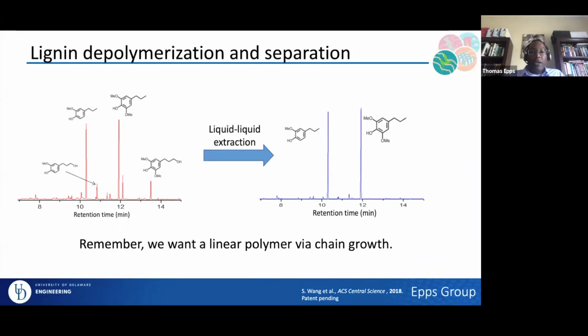So one of the nice things about doing catalytic depolymerization as opposed to, say, pyrolysis is that we can do it at much lower temperatures and in some instances even much lower pressures. The nice part about that is that we can get more selective bond cleavage in the lignin. So we can really cleave things like the beta-O-4 linkages, for those of you who are familiar with that. And that leads to a relatively small distribution of products when we look at the gas chromatogram. Now, hopefully one of the things that you can still see here is that our next step is functionalization.